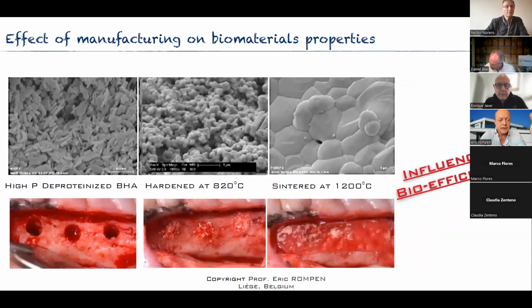Does it really have an influence on the bioefficiency of the material? I would like you to have a look at those three materials. Actually, it's the same material. It's our material. On the left part, it's just after the protein extraction process at the exit of our big and patented reactor to extract the proteins. It's a very rough material, but still not very hard. In the middle, the material has been hardened with a flash treatment at a very precise temperature. It's not sintered, it's just hardened with a flash treatment at 820 degrees. And the same material, when we heat it at 1200 degrees, we completely melt it and it becomes very smooth, like you can see on the right side of the image.